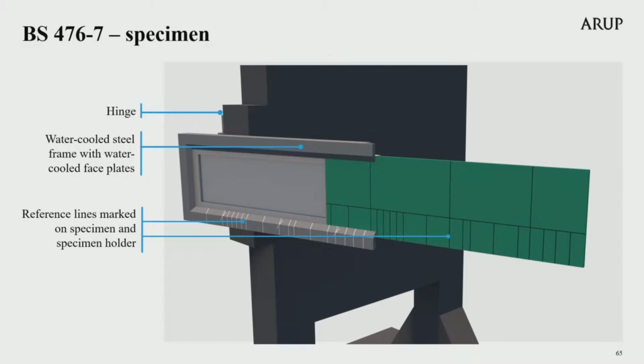Specimens are tested at full thickness, so long as they fit into the test frame. Where a material is more than 50 millimetres, it is cut down from the unexposed side to allow it to fit. In the test position, the specimen holder assembly is located at 90 degrees to the face of the radiation panel. The height of the specimen holder is such that the horizontal reference line marked on the specimen and shown on the screen here is brought to the mid-height of the radiation panel. The specimen holder is hinged to allow it to be swung horizontally away from the face of the radiation panel between tests. To assist with interpreting the results, the specimen is marked with reference lines before it is mounted into the test rig, and these lines are at set distances, as shown on the green face of the specimen on this slide.